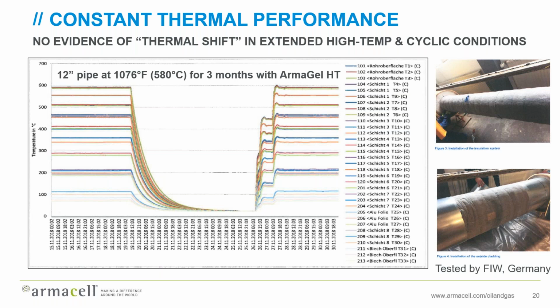A 12-inch pipe was insulated with multiple layers of ArmaGel HT and sat at 1076 Fahrenheit for 3 months. The temperature between each layer and on the surface was measured throughout that time. At the end of that test period and after some cycles, the temperature at each of those layers was unchanged. So in other words, there was no evidence of thermal shift at all over those extended high temperature and cyclic conditions. So if that question ever comes up, there is data to back this up, and we'll be happy to talk about that with you.